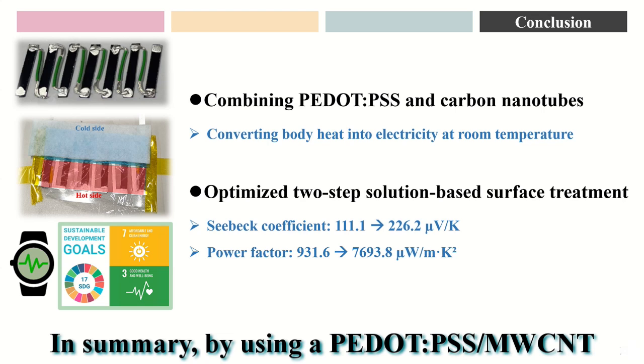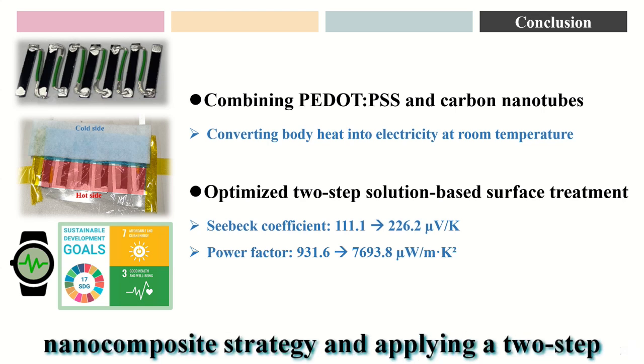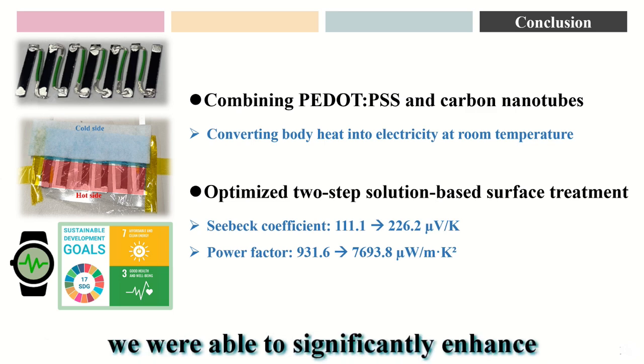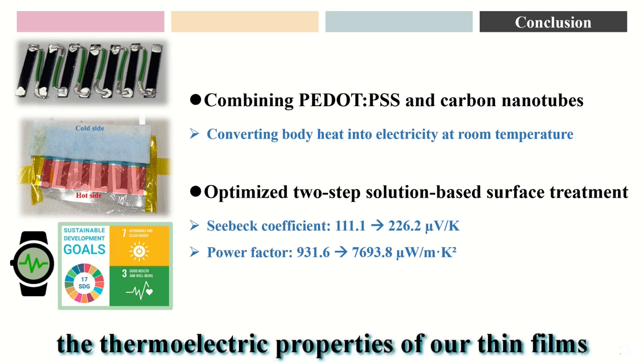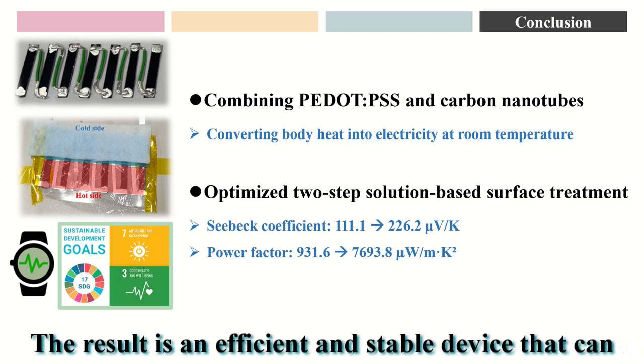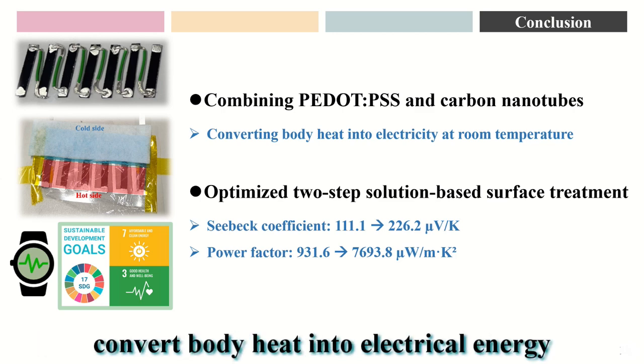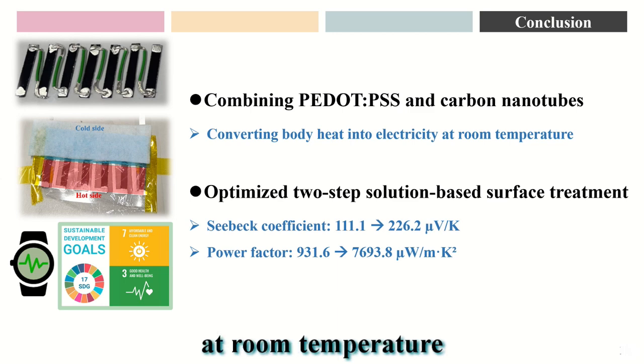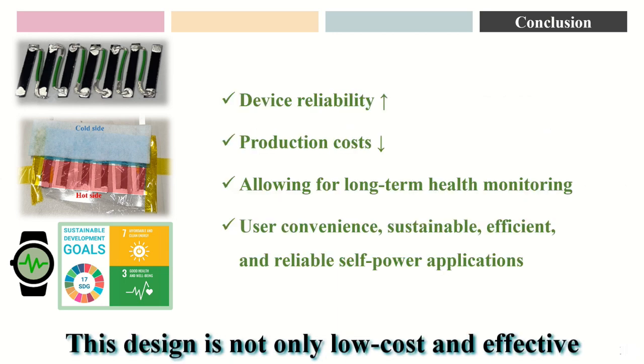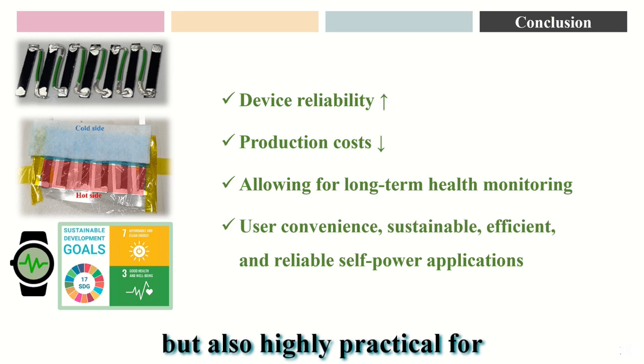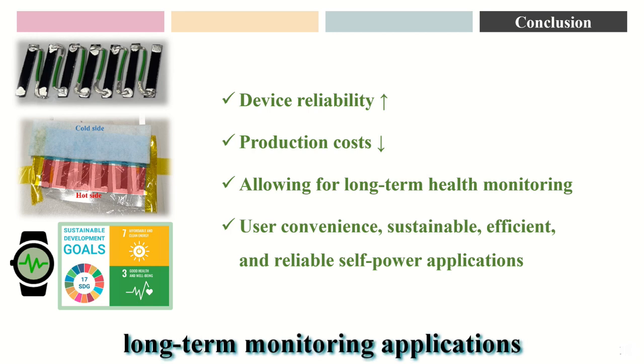In summary, by using a PEDOT:PSS multi-walled carbon nanotube nanocomposite strategy and applying a two-step solution-based post-treatment, we were able to significantly enhance the thermoelectric properties of our thin films. The result is an efficient and stable device that can convert body heat into electrical energy at room temperature. This design is not only low-cost and effective, but also highly practical for long-term monitoring applications.